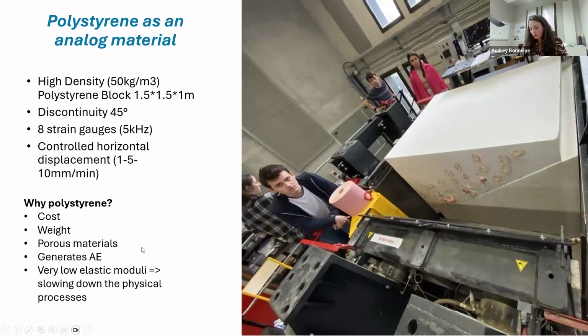And then there are the real reasons. So first, polystyrene is a porous material, which means that we can observe some compaction prior to the sliding on the surface. Then it can generate acoustic emissions. I'm not going to show you results from the acoustic emissions that we tried to measure, because some parameters still need to be adjusted. And also, last but not least, because it's polystyrene, it has very low elastic moduli, which means that all of the physical processes taking place during the sliding of the sample are slowed down, due to the very low elastic properties.